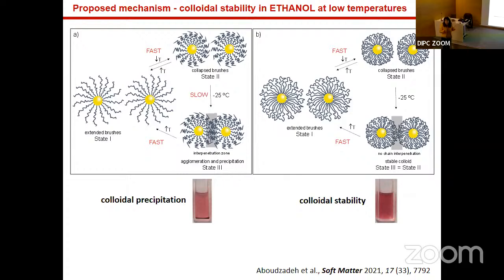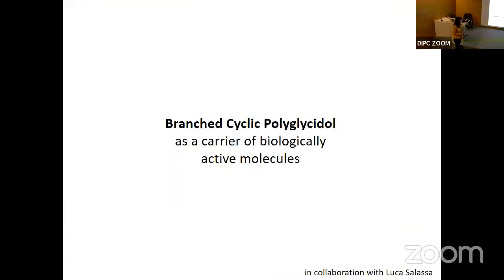Of course, it happens mostly on the linear polymers. They collapse because of the cooling. Then, very slowly, this is a very fast process, very slowly they start to interpenetrate, and they seem to be responsible for this precipitation. For the cyclic polymer, this is not possible, and probably this is an explanation for that. I have explained very briefly. There are more details here, but I cannot explain all this.